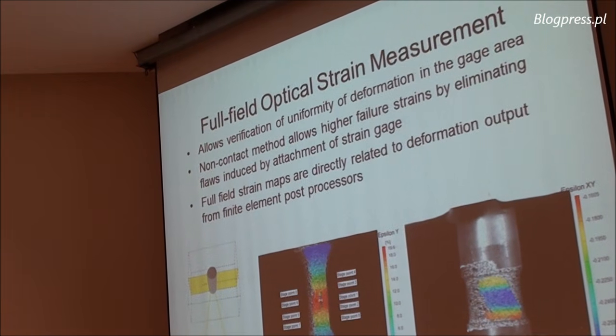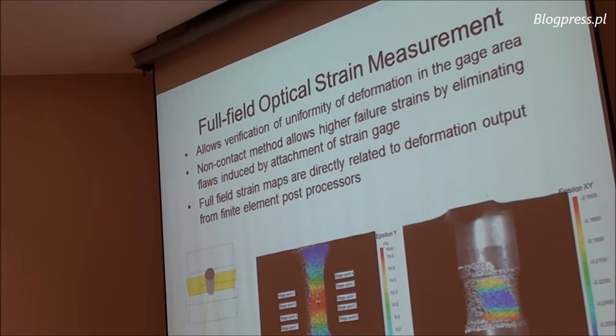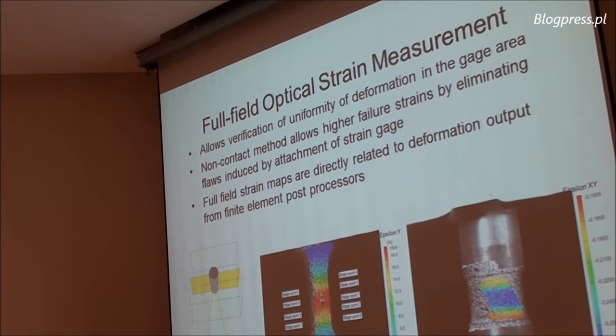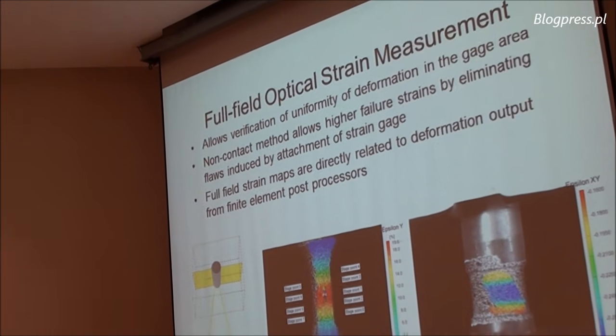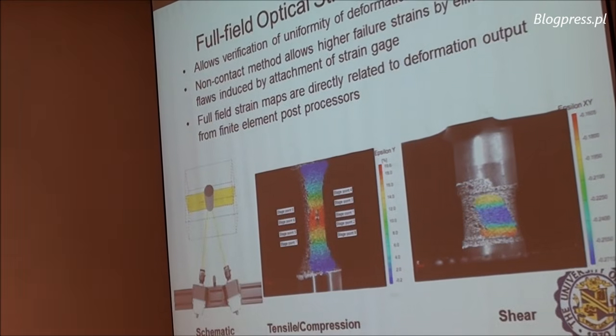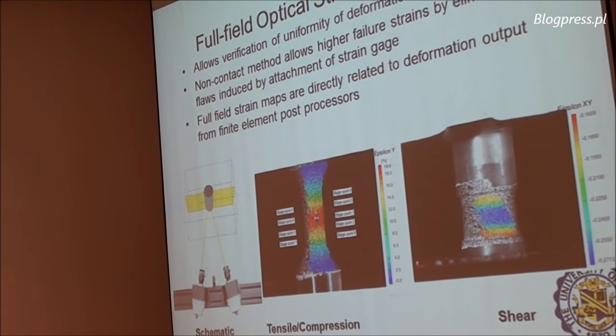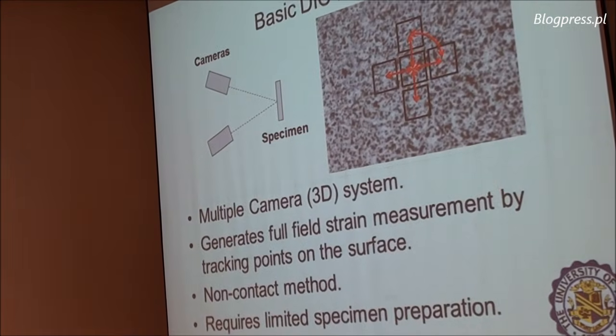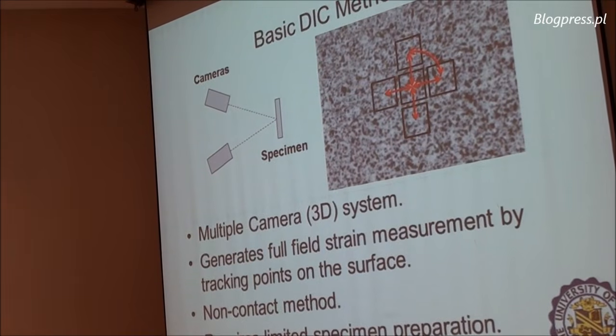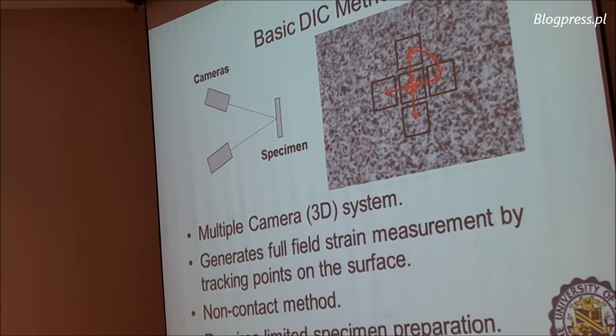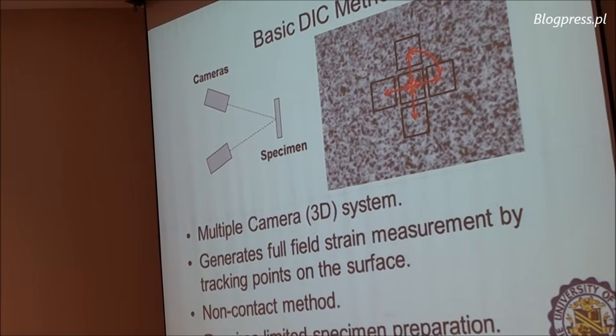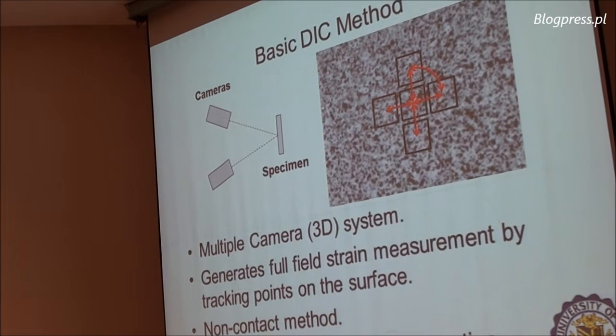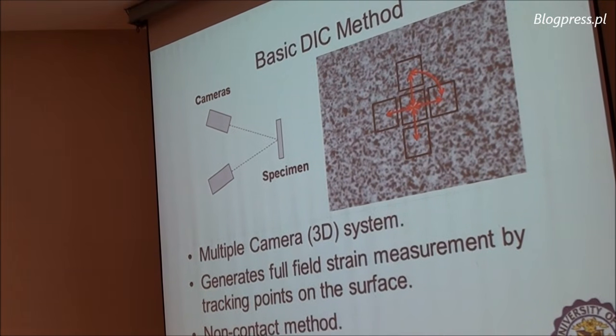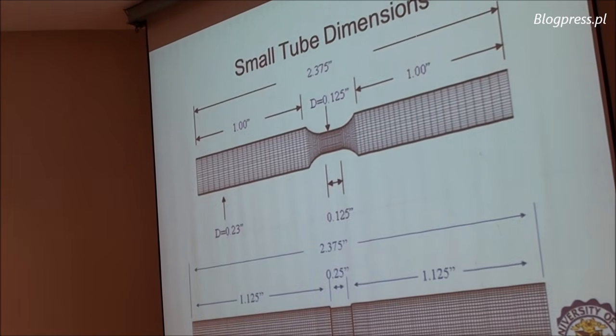So in order to characterize the resin material, we developed special small samples that we could get the results under tension, compression, and torsion for the shear. So we had a small cylinder, and we used a digital image correlation technique to observe the deformation of this material. I'm sure in your university you use digital image correlation widely. It used to be an advanced method of measurement, but right now it's very common, so I'm not going to discuss that.